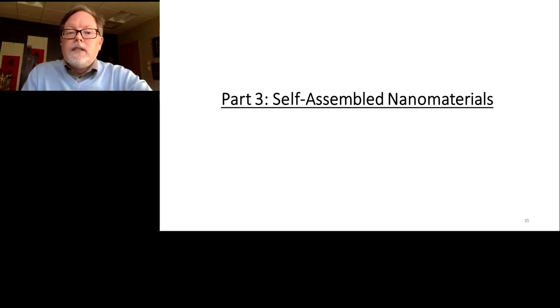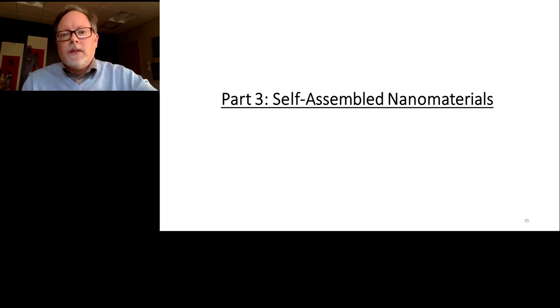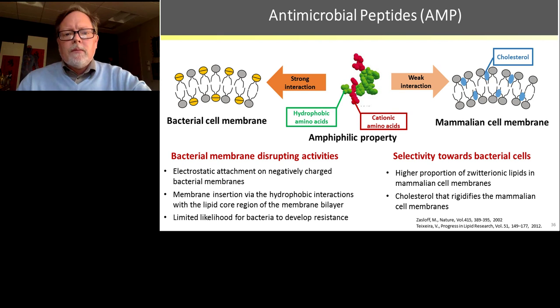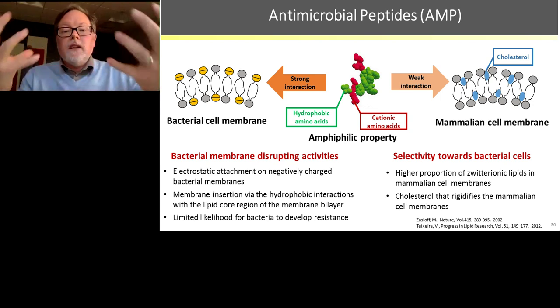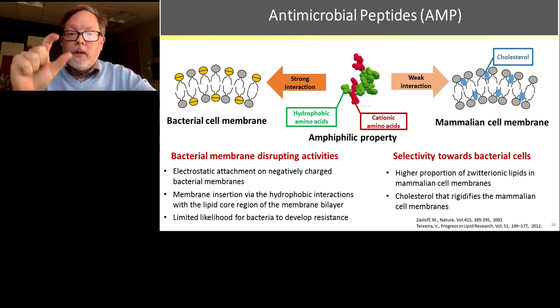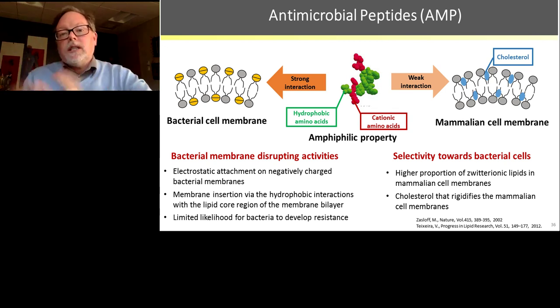So this is the field of self-assembled nanomaterials, which is growing and growing in popularity because it's sort of like a pre-programmed nanomaterial. You know it will self-assemble in a controllable way to kill bacteria. Our version of self-assembled materials we're using to fight bacteria are called antimicrobial peptides. So what we do is we simply take things like hydrophobic amino acids that can attach to the membrane of a bacteria. We then add a group that's hydrophobic, add a group that's hydrophilic so that it will self-assemble into a rod to then interject into the bacteria membrane, kind of stab the bacteria membrane and cause the inside to come out.